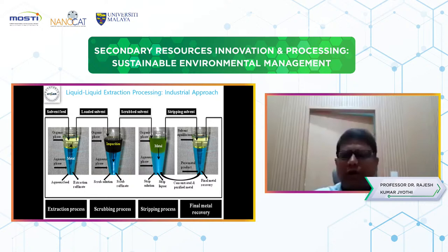To develop the industrial liquid-liquid extraction process, we need initial studies like kinetics, and here 5 to 10 minutes is more than enough to recover the dysprosium and neodymium. Then for reagent concentration, we are using only 0.1 mole, a very small concentration, and we can recover more than 90%. Then after the extractant concentration optimization, we go for the separation possibilities.